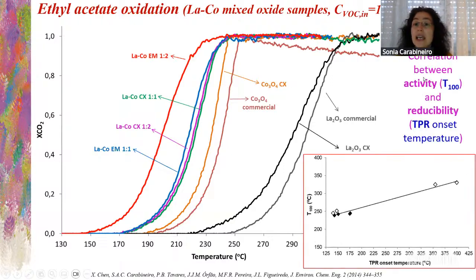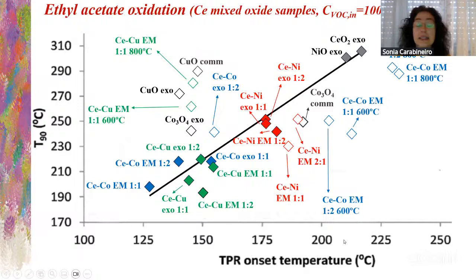And we obtained, again, a correlation between the activity and the reducibility by the TPR onset temperature. So here in white are the single oxides, and here in black, these two samples, are the results of the mixed oxides. So you obtain, again, a correlation with the reducibility of the single oxides. Okay, this might seem a little bit complicated, there are too many samples. It's for cerium mixed oxide samples: cerium with cobalt, cerium with copper, cerium with nickel, and also the single oxides.